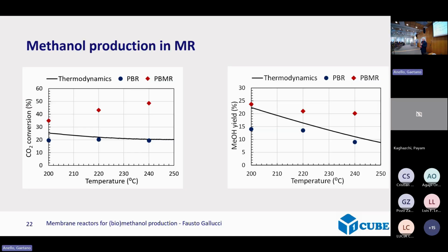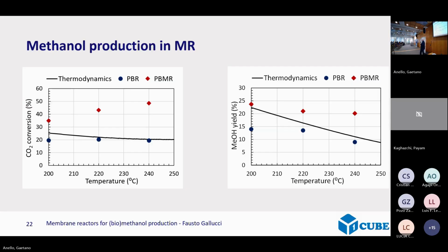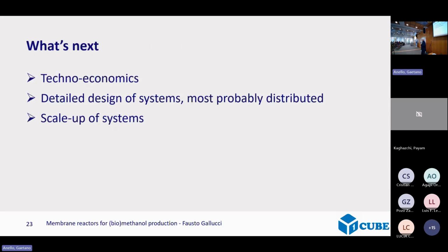Now, what we did here is producing methanol in small reactors, TRL3, closer to 4. Okay, so we are speaking about membranes of around 15 centimeters. So what is next, and this also will be part of the BioMeGaFuel project, is to take this membrane and scale. So in this project, Gaetano is working on the scale up of these membranes, and we will be testing the reactor at TRL5. So compared to the previous experiments, we want membranes of at least 30 to 40 centimeters and many membranes inside the reactor.